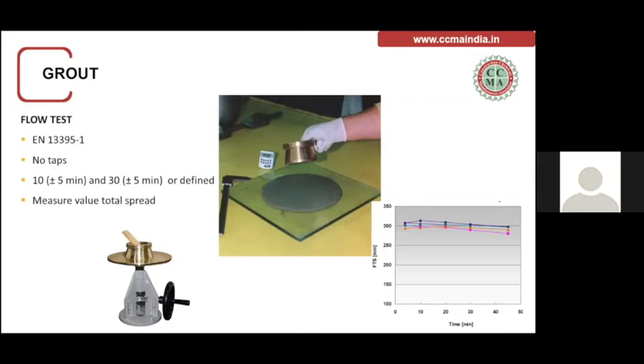on the glass plate, and then after some time it is taken off, and then the spread is measured. So initial 10-minute spread should be close to 300, and after 30-minute it should slightly reduce, like 280 to 290, like this. The flow should be achieved. In case the flow is not getting achieved, there are high chances that the grout would not flow properly and the joints would not get filled.